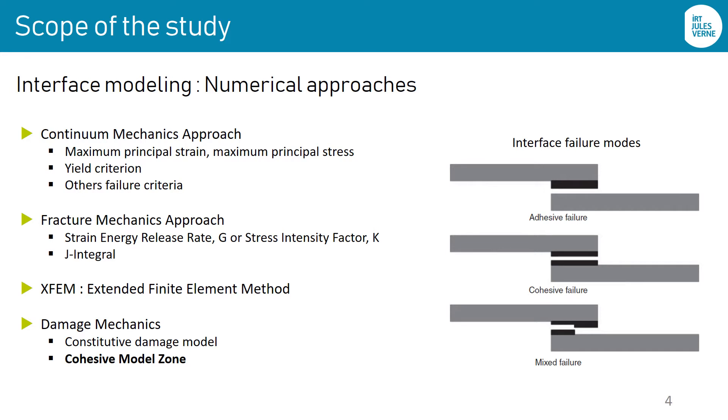More sophisticated methods are also used as the XFEM method. The most robust methods are certainly based on damage mechanics. The use of a continuum damage model could be expensive given the formulation of the models and the high number of parameters these models are constituted of. The cohesive zone models constitute a good compromise between phenomenon representativity and computational efficiency.